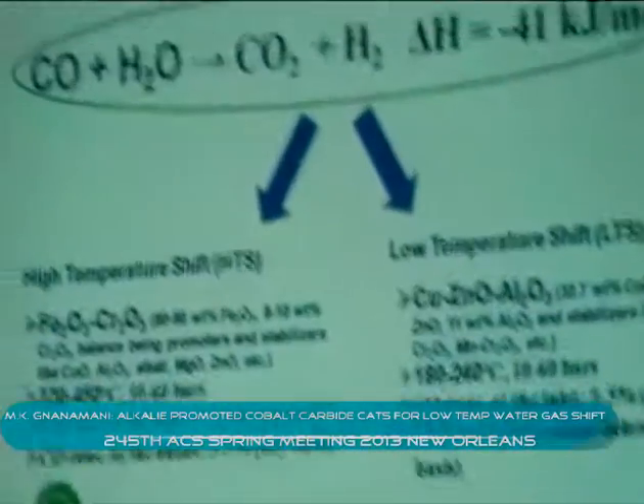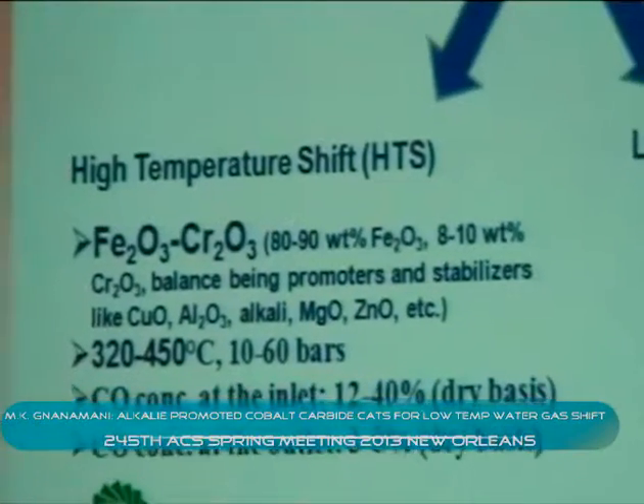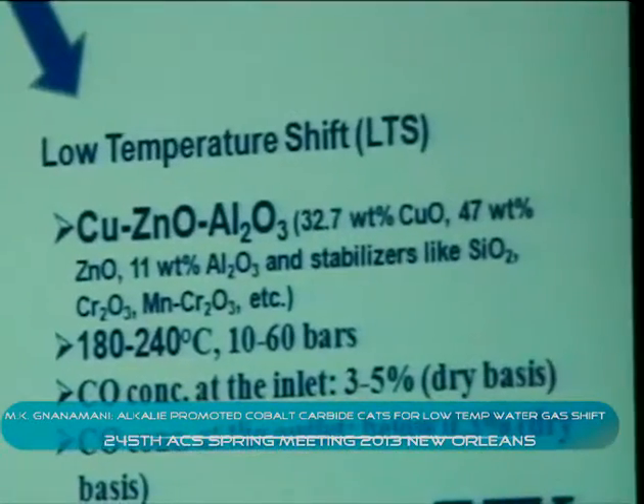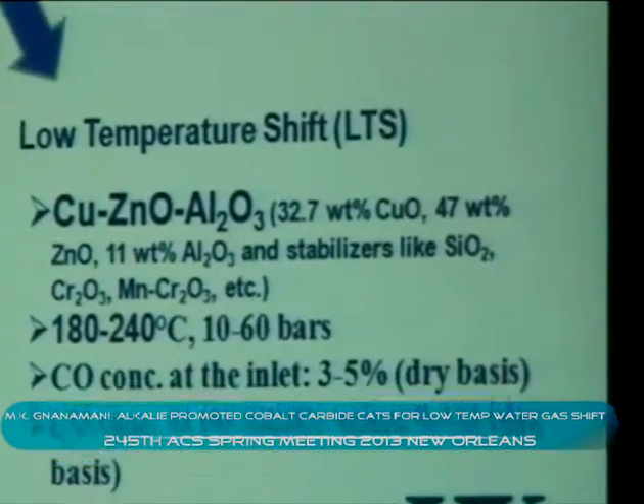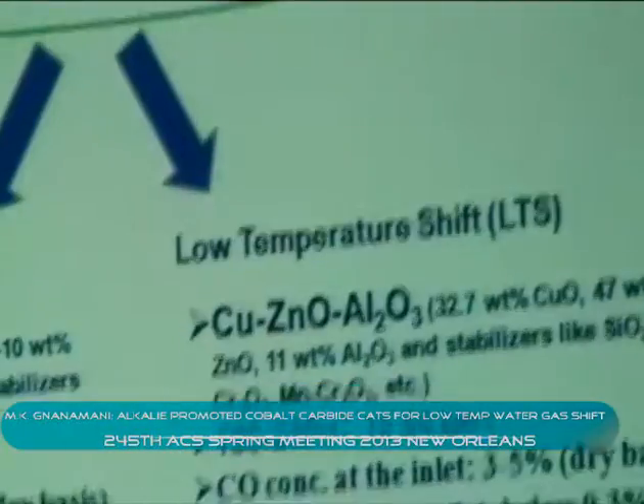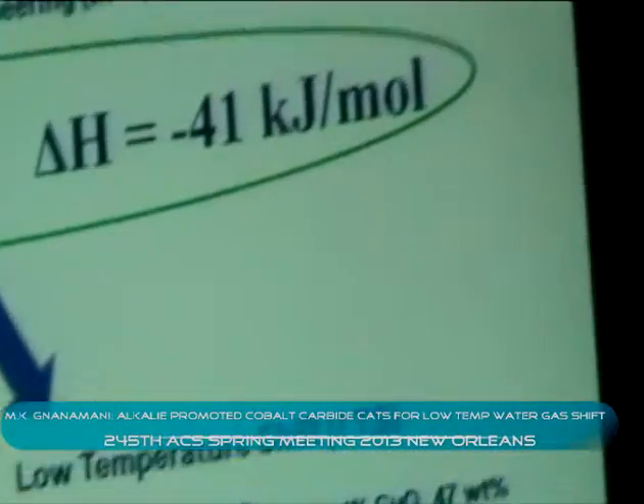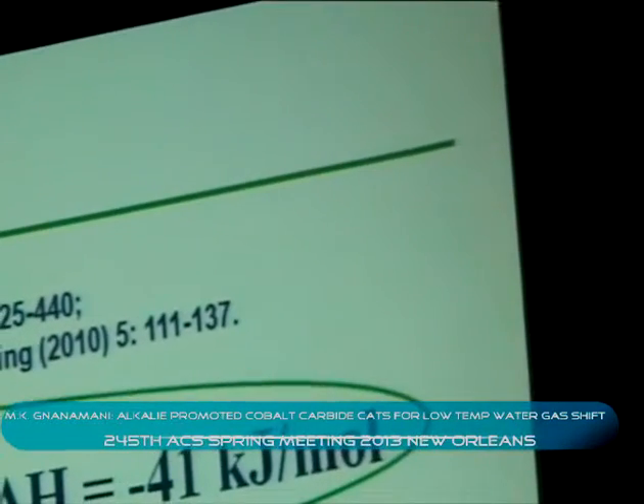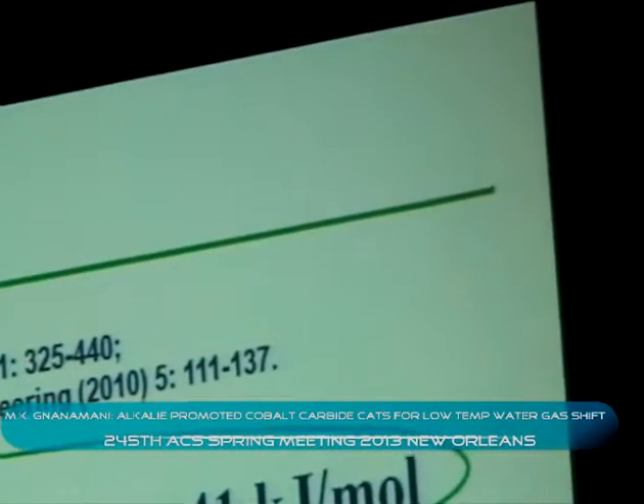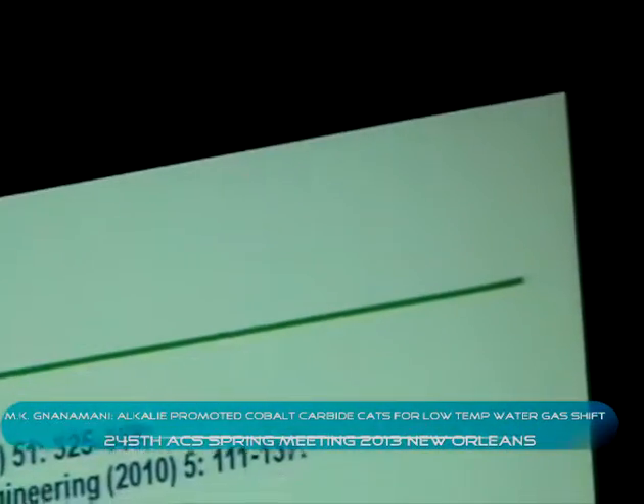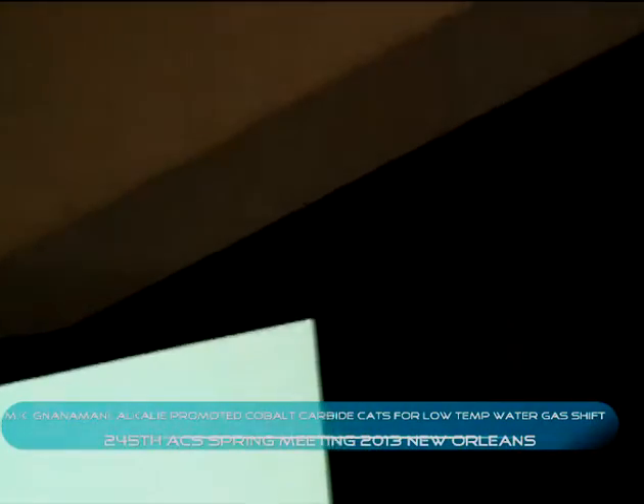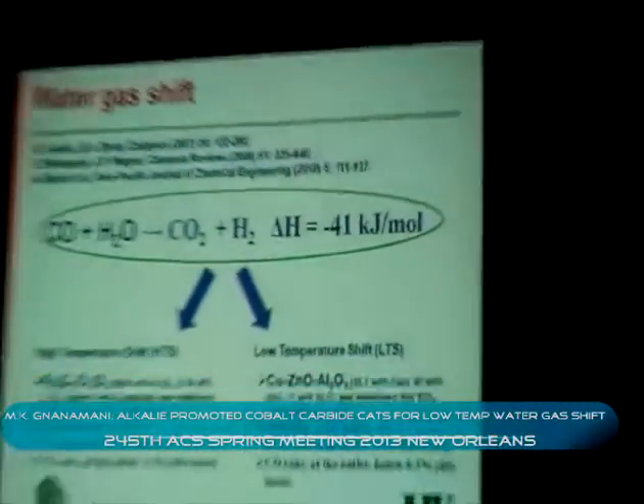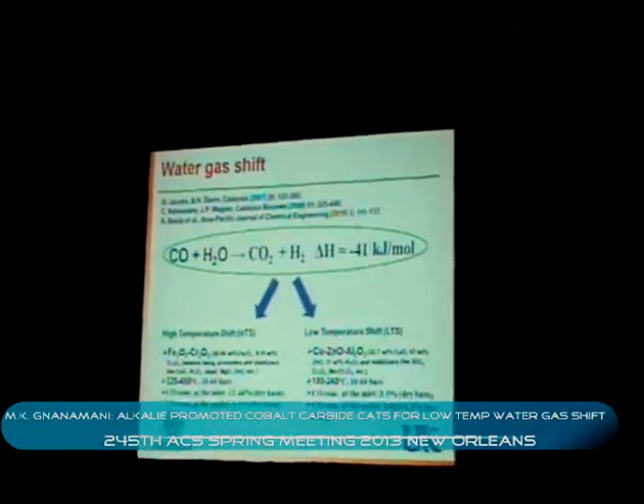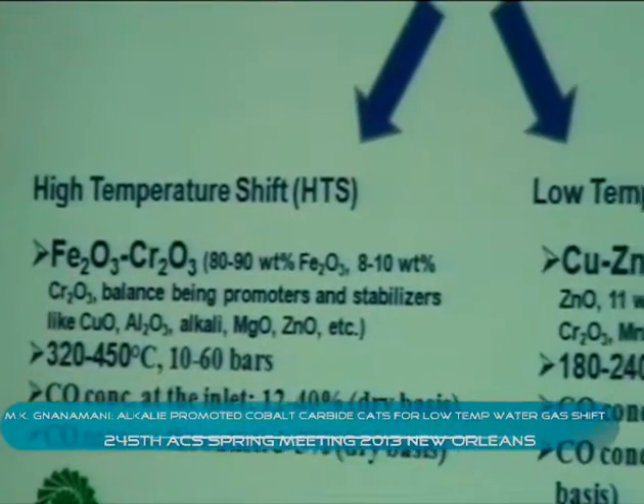In the industry, there are two different catalysts being used. One is the high temperature shift and the other is the low temperature shift. In the high temperature shift, iron and chromium based catalysts are being used, with 80 to 90% iron and 8 to 10% chromium, with stabilizers like copper, aluminum, and other alkalis. The typical conditions for the high temperature shift are 320 to 450 degrees, 10 to 60 bars. And in the case of steam, at high temperature, the CO inlet will be at 12 to 40% on a dry basis, and the CO coming out from the high temperature shift reactor will be like 3 to 5%.